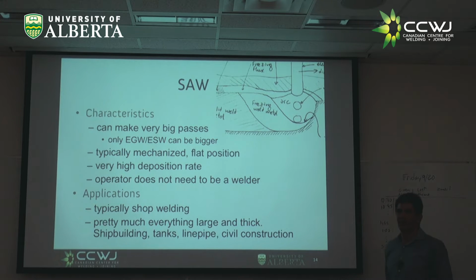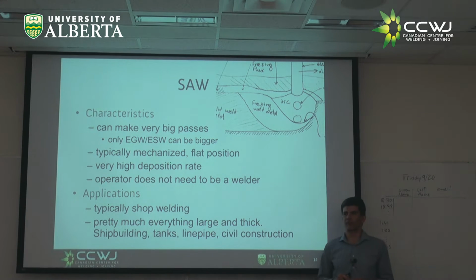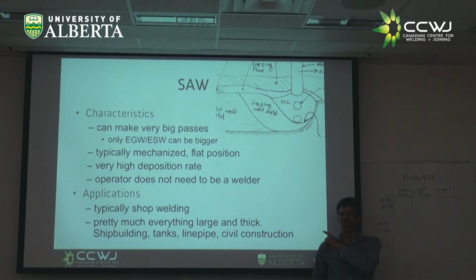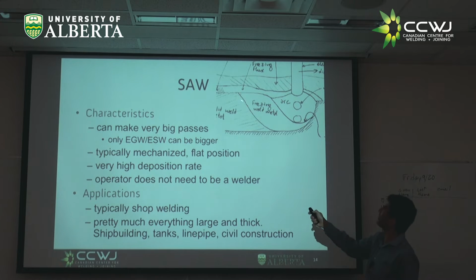Shipbuilding, tanks. Remember when I told you the story about the T-34 tank, about the Soviets, 7-to-1? The Panzers were better, or maybe not, because the Russians could make more than 7-to-1. It's because it was subarc welded. You end up with all this slag. When they first demonstrated the welding of the T-34 to the Soviet powers that be, they took the powders out, and it looked horrible because they saw all the slag. And they said, this is never going to work. Then the engineer comes, chips all the slag, and it's this beautiful, shiny weld, and the rest is history. Very interesting.